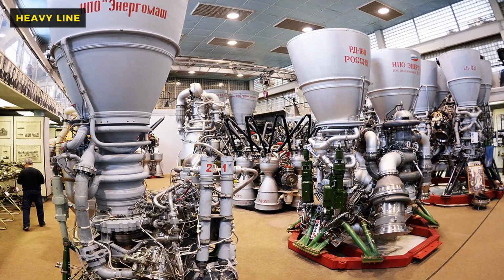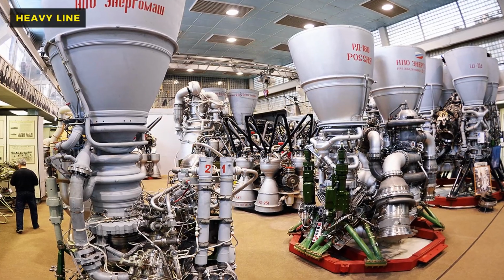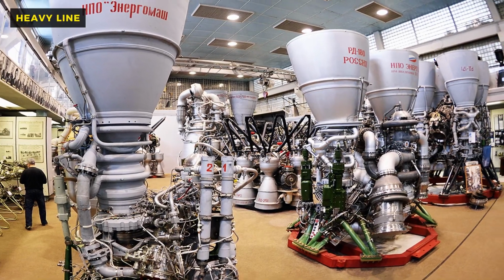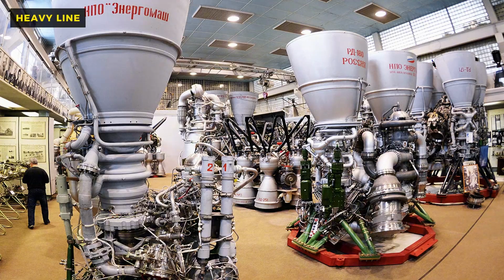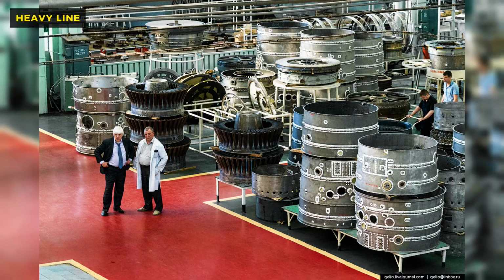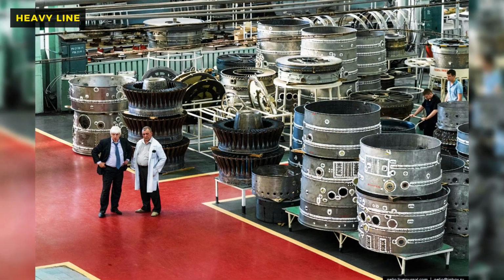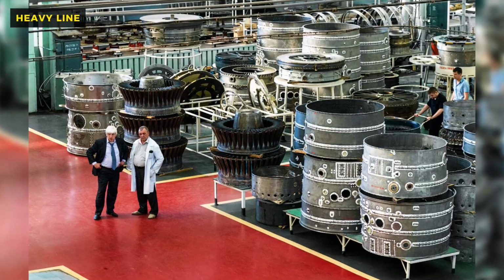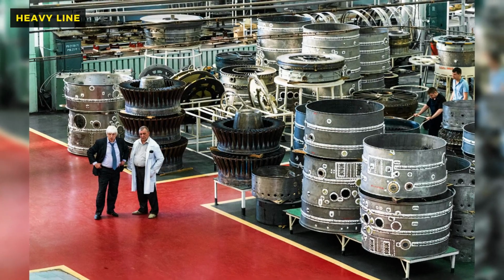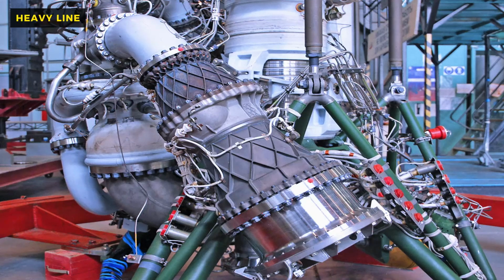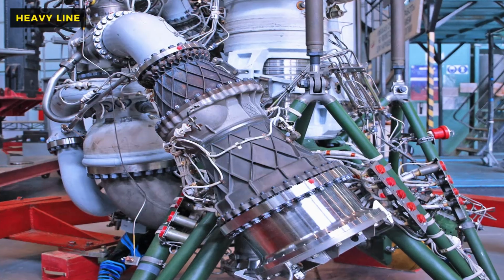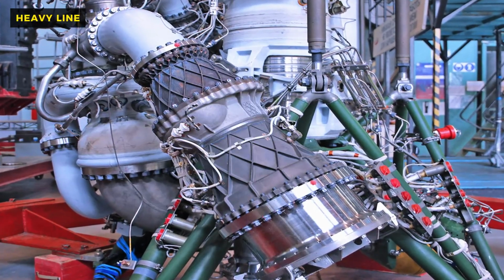The entire assembly is placed in a vacuum furnace and heated until a thin layer of gold palladium or similar brazing alloy melts and fuses the two shells together. If there is a single gap in that braze, a single bubble of air trapped between the layers, the heat transfer will fail at that spot, and the engine will destroy itself in milliseconds.